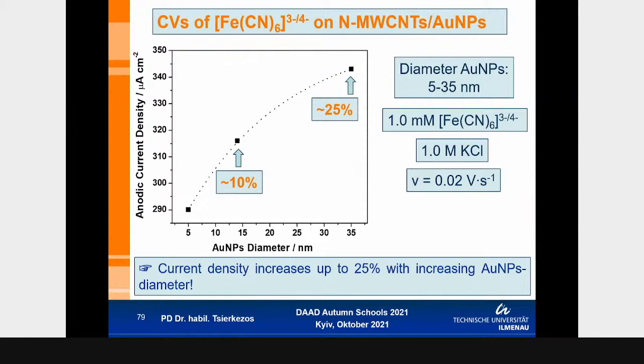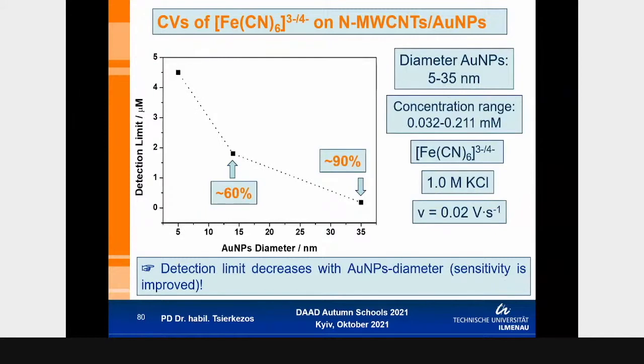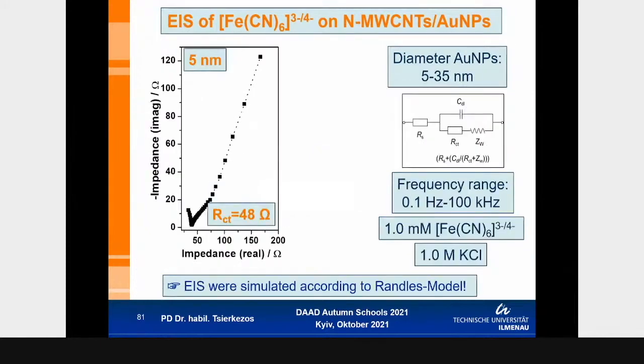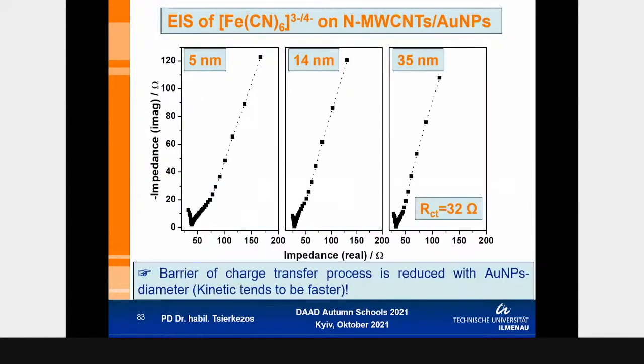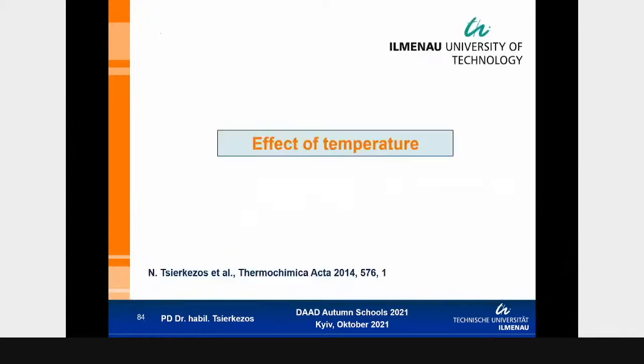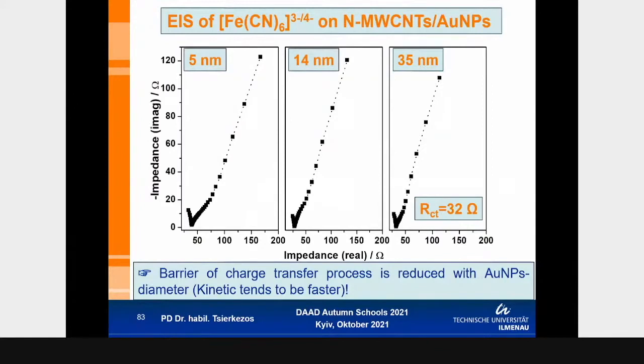Once more, the graphical representation of the variation of the anodic current with the diameter of the gold nanoparticles, and the same with the detection limit of the electrode. You see that with the modification of carbon nanotubes with gold nanoparticles having a diameter of 35 nanometers, we observe an increase of the sensitivity of about 90% of the sensor. The same has been confirmed by using electrochemical impedance spectroscopy. You can see that the barrier of the redox process is decreased significantly by using gold nanoparticles having greater diameter.